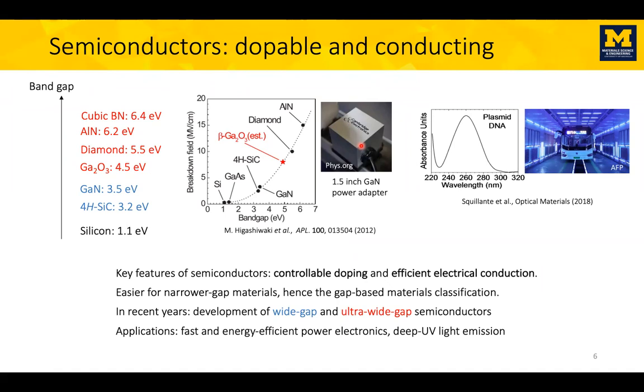Another thing you can do with them though is you can also use them to emit deep ultraviolet light. And when I say deep ultraviolet, I mean a wavelength of around 260 nanometers, which corresponds to an energy of 4.8 eV. You see, you must have 4.8 eV in order to emit this kind of photons, right? And the reason we want this wavelength is because what I'm showing here is the absorption spectrum of DNA. And DNA base pairs absorb resonantly at this wavelength.